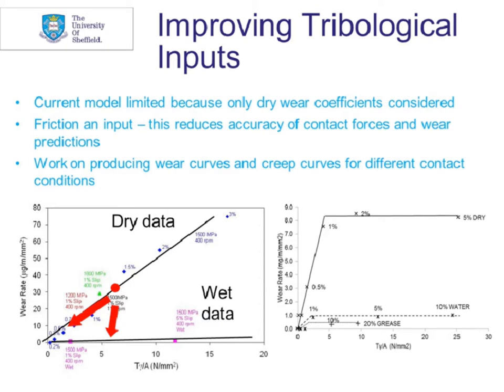But if, for example, you had a wet condition, actually you need to be jumping on to that much lower wear rate curve at the bottom of the graph. So immediately you are getting some inaccuracies creeping in. And of course, going back to friction being an input, if you're estimating the friction coefficient and you haven't got it quite right, that initially can give you some errors, because then your simulation will be calculating the wrong forces in the contact. So we needed a much better understanding of how friction and wear vary with different third body layers to improve our approach to modelling.